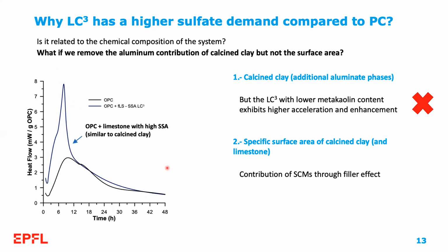So in this case, we were able to confirm that it is the contribution of the surface of the SCMs, through what we call filler effect, that explains the higher sulfate demand, or the increased sulfate demand, of LC3 and in general of any blended cement. But the question is then how the filler effect is linked to gypsum depletion, because filler effect is something that we normally relate to hydration reaction enhancement, and this is a separate chemical reaction involving alumina.